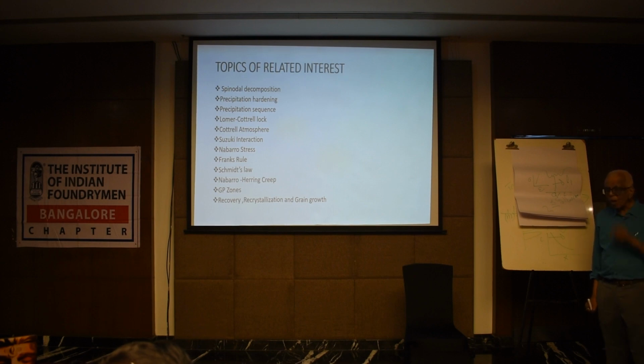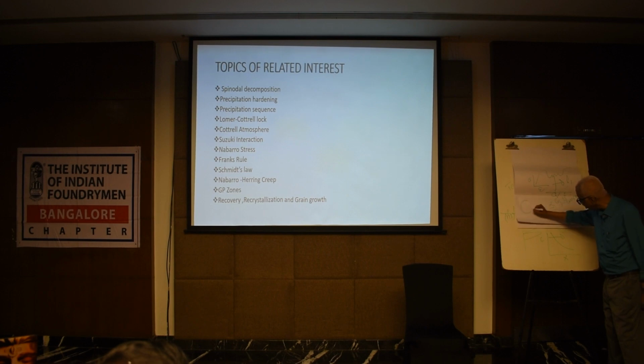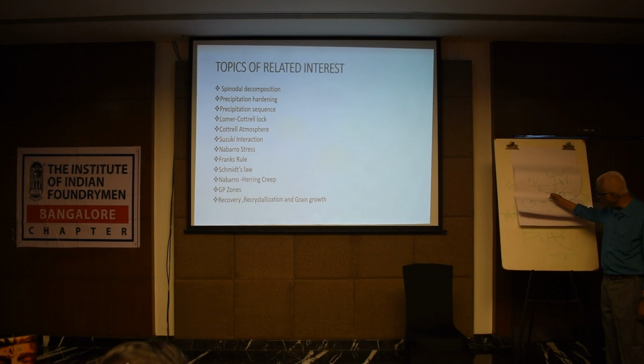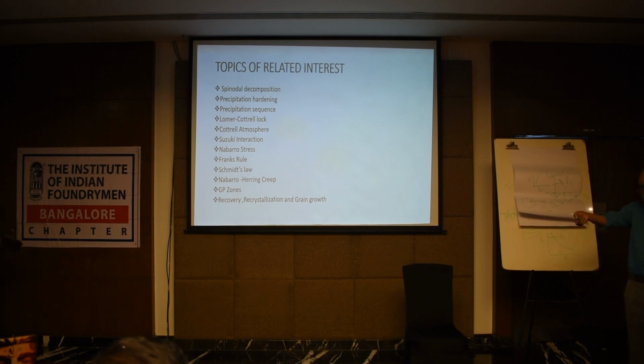What happens is when you have two precipitates, a big precipitate and a small precipitate, close by, the small precipitate dissolves. There is a flux of atoms to the big precipitate. The small one will shrink and die, the bigger one will expand. That can be applied to economics also, how big companies swallow small companies. Darwin's theory applied socially. The bigger ones grow at the expense of the smaller ones, or the richer get richer, and the poorer get poorer, shrink and die. That's grain growth.